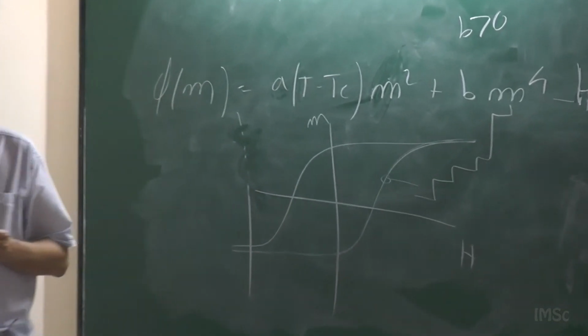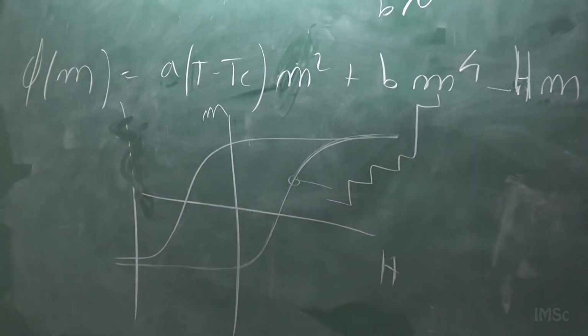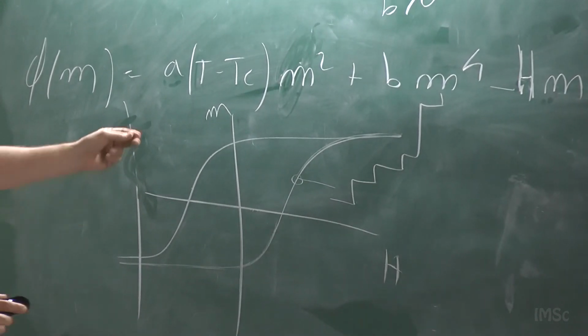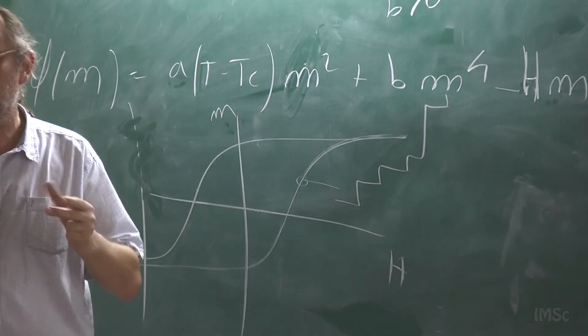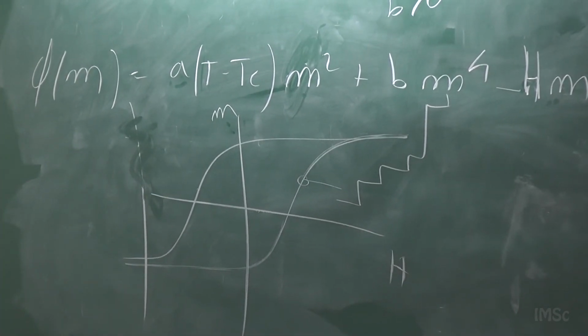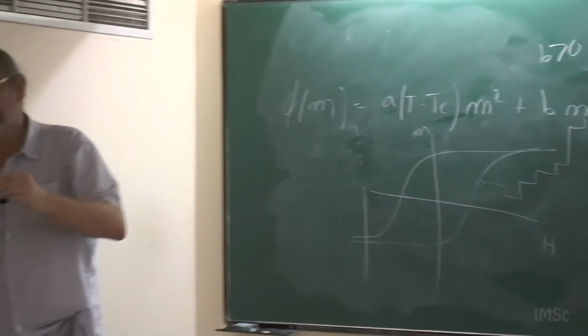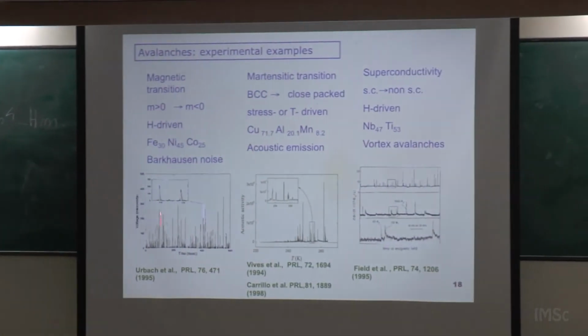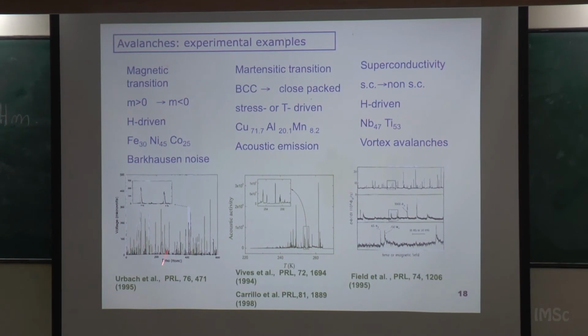And this technique is what is called the Barkhausen noise measurement, which is a technique that measures not the magnetization, but the changes in the magnetization. You put a coil, and every time there is a change in the magnetization, you get a pulse, and you measure the size of that pulse. This is the Barkhausen noise measurement, and this thing here is a train of jumps measured by this technique. It is a voltage in a coil when you drive the system very slowly. This was one of the first papers, but there have been many studies since then. There are groups that have done really very nice studies of Barkhausen noise, and they have characterized this avalanche behavior very well.